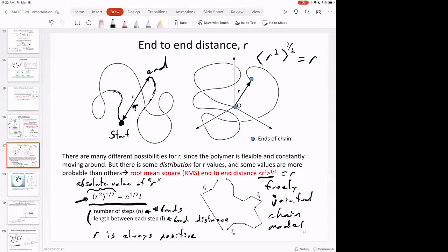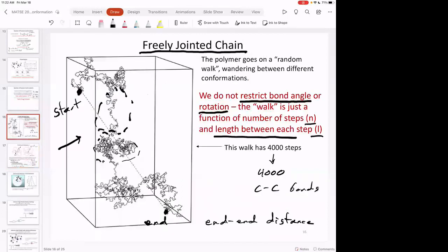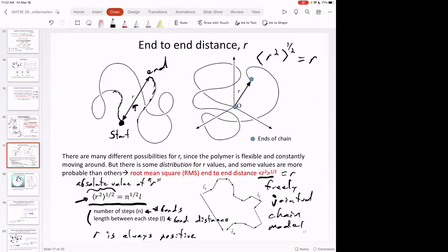And it turns out in a lot of cases, just looking at a polymer that's all coiled up, and it might look something like this, characterizing that end-to-end distance is important. That's used in rheology, that's used in polymer physics. It's a really nice descriptor of how big the coil is, because it's hard to figure out the volume of this thing, right? It's hard to figure out exactly what's going on. Contour length and fully extended chain length aren't very realistic descriptors of what a polymer really looks like. And so we use this end-to-end distance as a descriptor of the coiling of the polymer chain. And the end-to-end distance will change depending on the situation. And of course, it depends on the molecular weight.